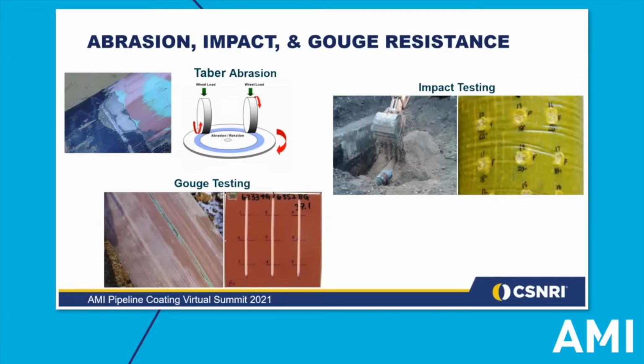Another source of damage is gouging, also referred to as shear scratching. A rock or other obstruction protruding into the drill hole can result in a sharp gouging force on the coating. Three distinct failure modes can occur: crack propagation over time through the corrosion coating, or instantaneous penetration down to steel without pipe damage, or penetration to the steel resulting in metal loss.